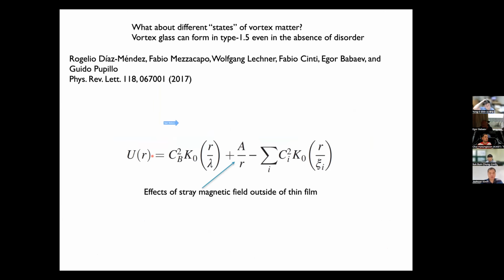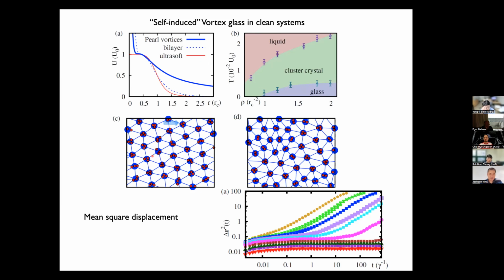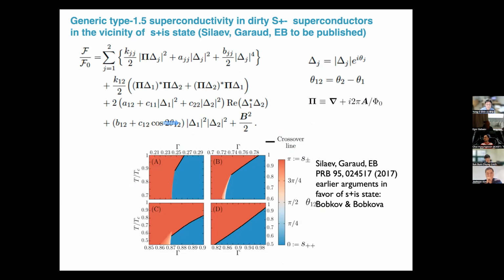What is more, another thing I wanted to mention about these vortices: in an ordinary vortex matter, which was well investigated, if you have impurities you can have vortex glass if and only if you add impurities. But what is also interesting about type 1.5 regions is that you can form vortex glass in certain conditions without any quench disorder, without any type of impurity, just as a consequence of intervortex forces. This was another of our works. We can show that you can form vortex glass in a translationally invariant clean system just as a consequence of interaction forces.